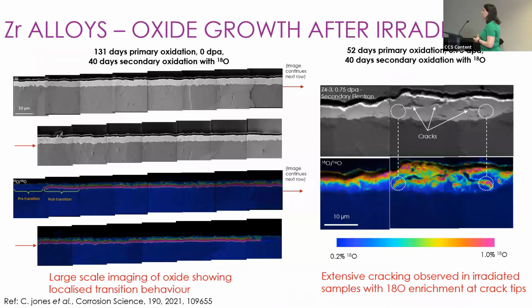So the real aim of Chris's project was to look at the growth of the zirconium alloys after irradiation. Obviously, these zirconium alloys are going to be subjected to a lot of neutron irradiation. Does that have an effect on how this oxide grows? So Chris had a whole matrix of samples, some which were not irradiated at all, and some that were irradiated to various levels of displacements per atom. And this irradiation was performed at the Dalton Cumbrian facility using proton irradiation as a proxy for neutron irradiation.